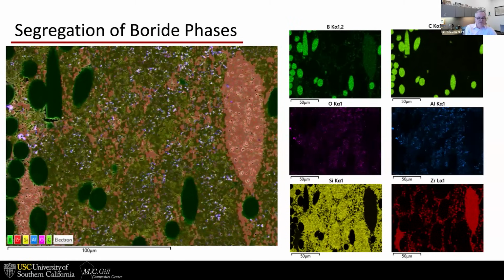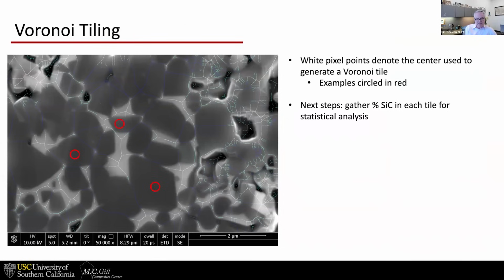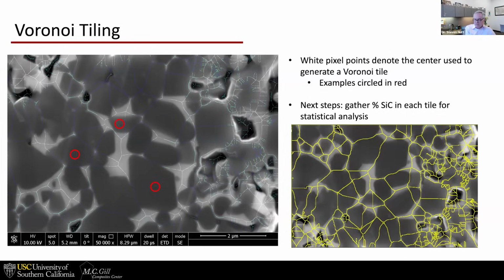oxygen, silicon. All right. One of the challenges with any composite is how do you measure the uniformity of the phase distribution? You can look at it, and by eye, you say, well, that's more uniform than this other section on the left. But there are ways to quantify this, and it involves some tiling or tessellation tools, where you subdivide the microstructure into small regions. And this is one type of tessellation called Voronoi tessellation. And that will enable us to actually measure how uniform the dispersion is in different iterations of the production.